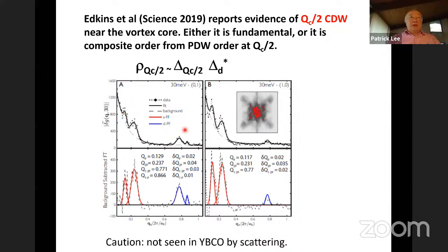Okay, so now you're faced with two choices. The first is that the original Q charge order is not fundamental. There's another order which is more fundamental, and that somehow creates the one that we saw ordinarily, which is actually only a harmonic of this more fundamental one. That's not very appetizing, I think. Now, the pair density wave immediately gives you that explanation, because remember, the pair density wave order we have is exactly half of the charge density wave order, by the Landau argument before.